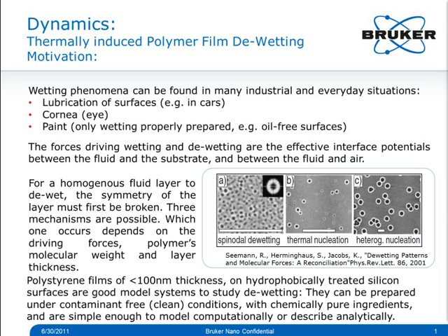in this experiment, thermal. The sample is a piece of silicon wafer, chemically treated with a hydrophobic layer and a thin polystyrene film on top. Typically, the sample is prepared by spin coating. The hydrophobic treatment of the silicon and the molecular weight and thickness of the polystyrene can be varied to explore